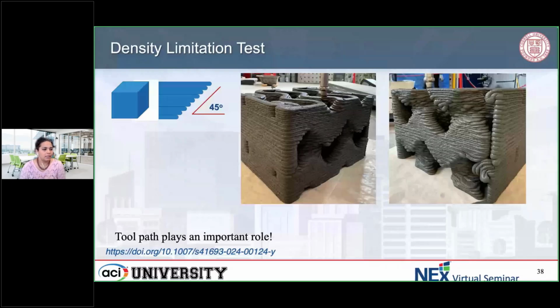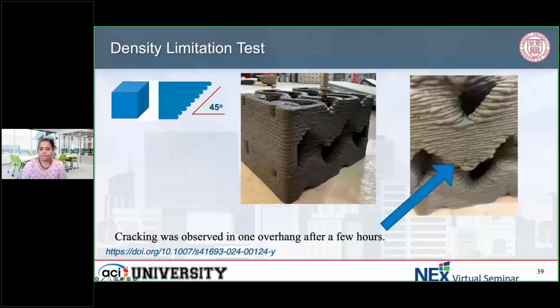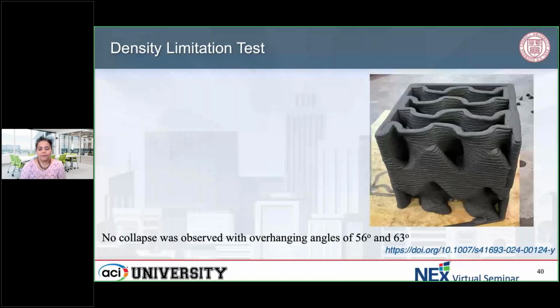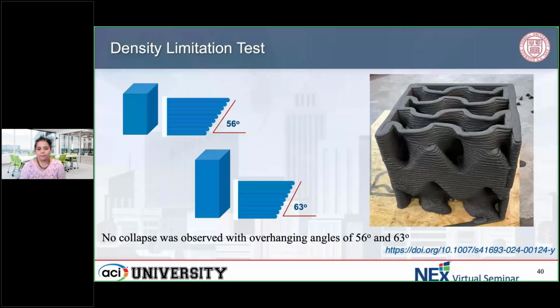But it also happened that this 45-degree geometry had some cracking within a couple of hours. It could be because the cantilever was too much for it to hold, but it could also be some issues that happened with this specific print. But with the 56-degree and the 63-degree, we were able to print them without any challenges.